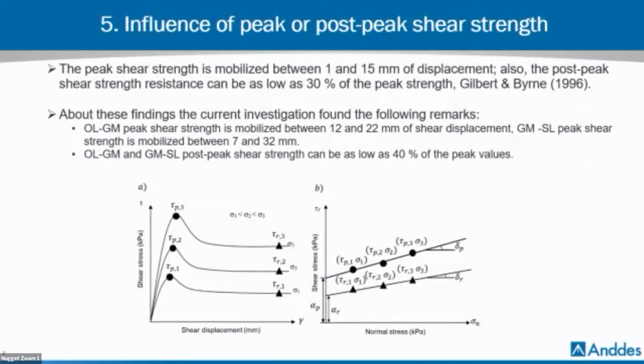What happened with this information in the slope stability analysis? The limit equilibrium method is commonly used to evaluate the stability of the heap leach pad. In this method, the interface is modeled as a continuous element like a soil layer. The analysis criterion that is most widespread and accepted in practice usually assumes that the mobilized shear strength can reach or exceed a peak shear strength for the materials. Thus, post-peak shear strength is usually considered in stability analysis.